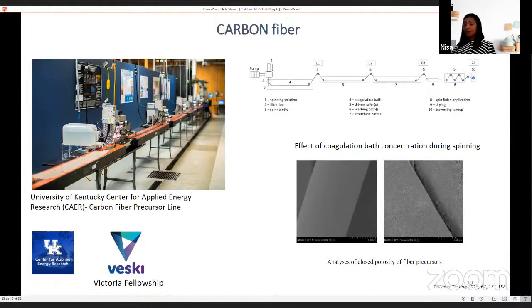The spinning facility at the University of Kentucky is a very specialized one, and they have more than a decade of experience in fiber spinning and fiber science. We conducted various spinning studies by changing the coagulation conditions. In our study, we used 80% organic solvent. In another study, we changed the bath concentration to 77.5. And we also developed a new method to measure the porosity of the fibers during the fiber spinning process. So if you are interested, please check our article to learn more about this porosity measuring technique.